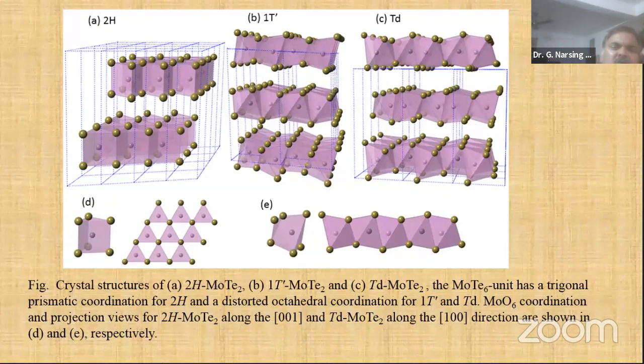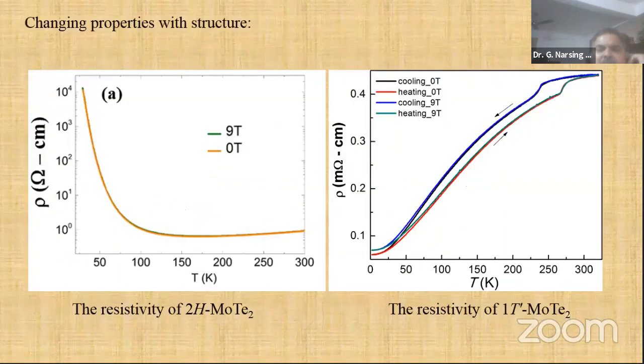Here we can make two different materials at room temperature itself. One is stable at room temperature, one at low temperature. Depending on the material processing conditions, we will make these two, and depending on the measuring conditions, we will get these two. So that's two different polymorphs. Okay, you can see now clearly.